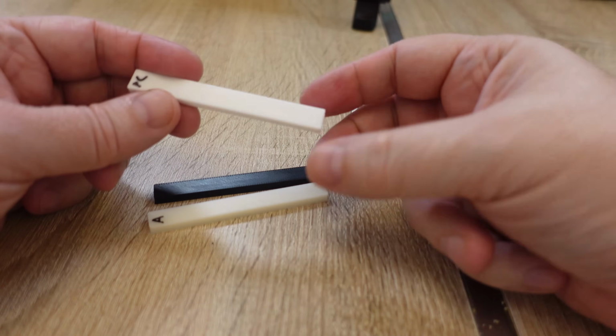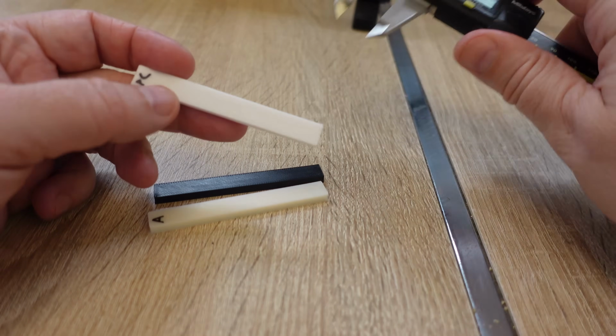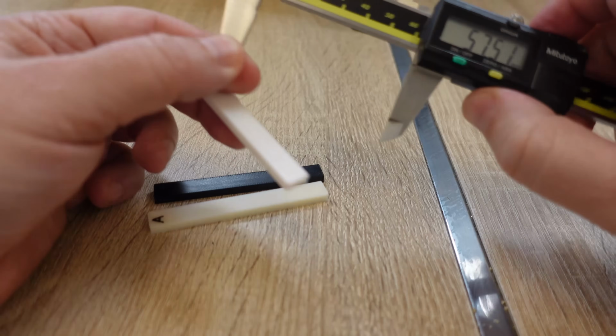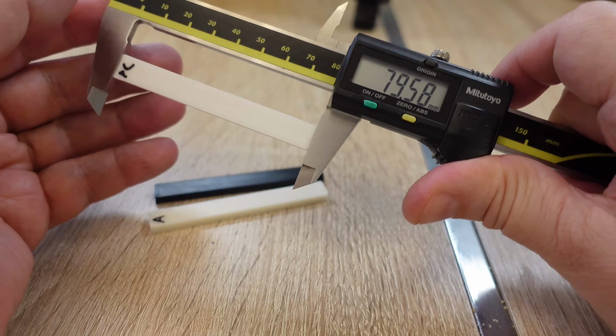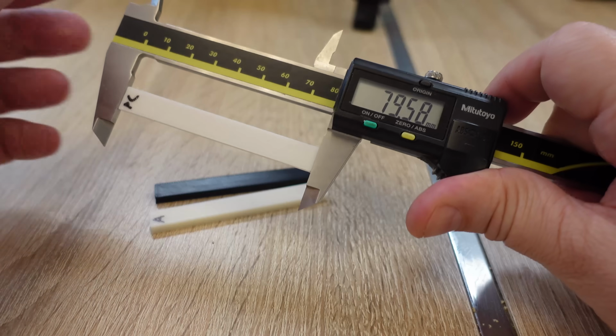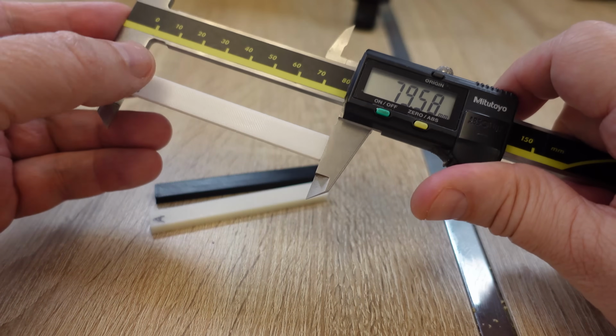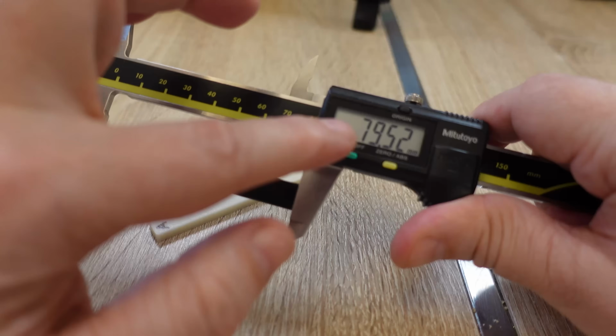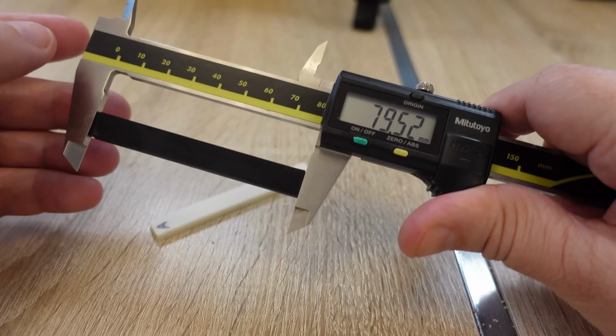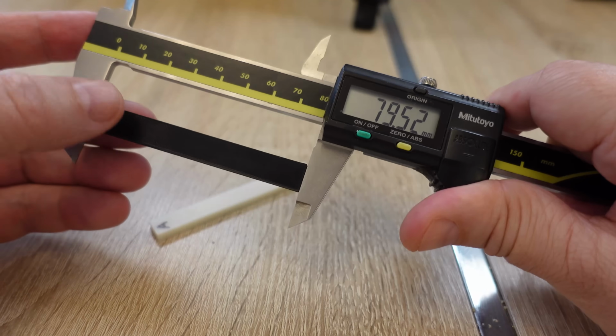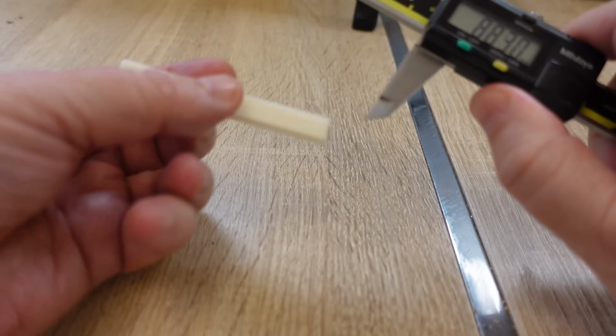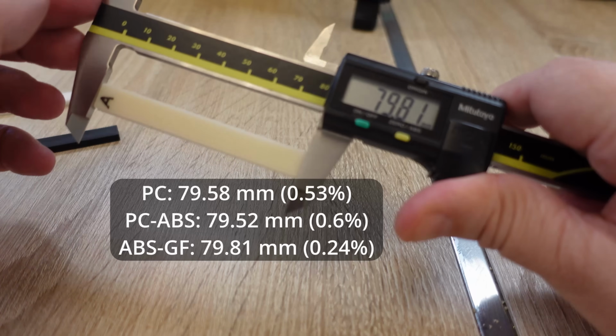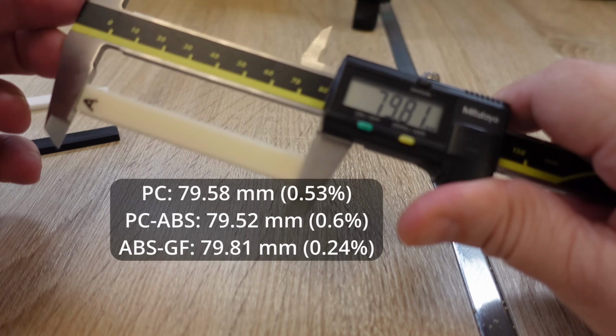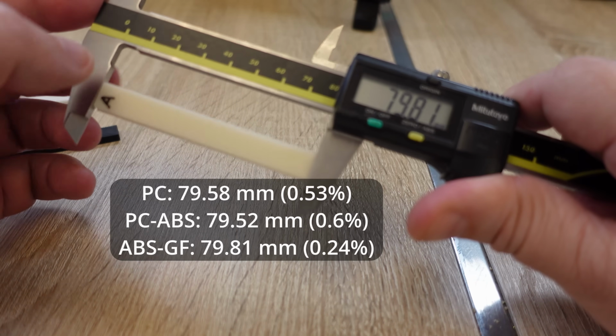Let's check the shrinking. I can feel some elephant foot and I will measure above it. The design length is 80 mm. Polycarbonate 79.58, which is very similar to the average ABS shrinking. PC ABS, the shrinking is bigger, that's why some companies recommend high chamber temperatures. And this should be the most accurate. 79.81, so there is some shrinking, but much smaller than without fibers.